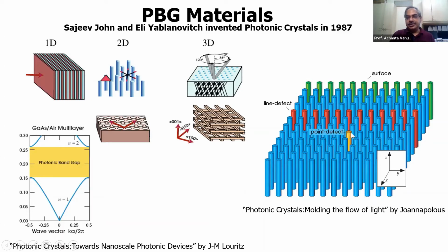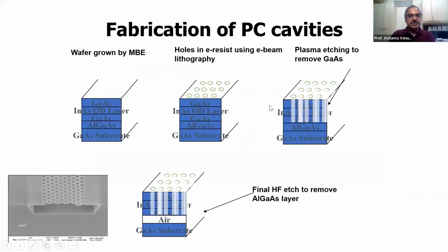Just by modifying one of the rods, one of the lattice sites, you can make a point defect. Similarly, if you want to guide light from one side to the other, you modify a row of these rods, so you get a waveguide, which acts like a line defect and can help you guide light from one part of your photonic crystal to the other. So it's possible to make that kind of cavity.